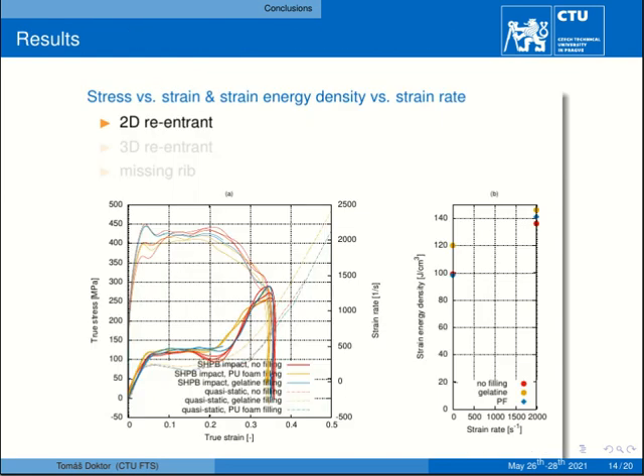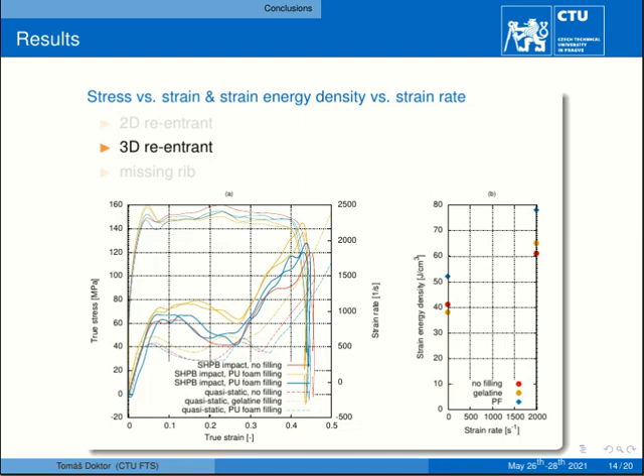Now briefly to the results. From the SHPB apparatus and its instrumentation, stress-strain curves were obtained, and from the stress-strain curves the strain energy density was evaluated and plotted against the strain rate. For all the groups of samples, the results show a slightly positive effect of the filling material on the strain energy density.